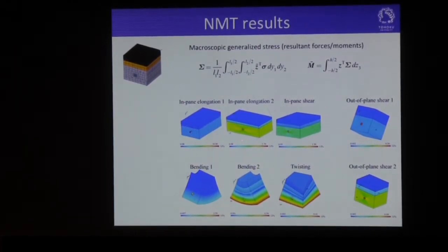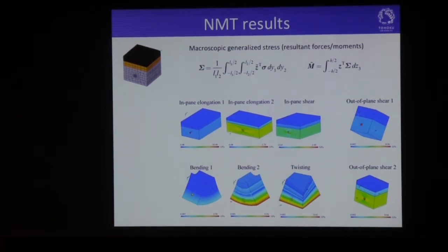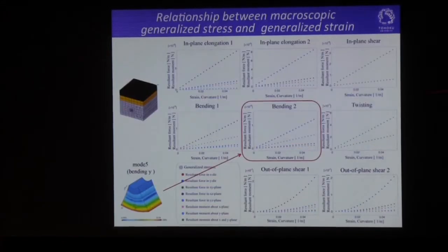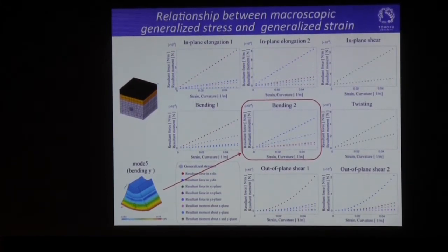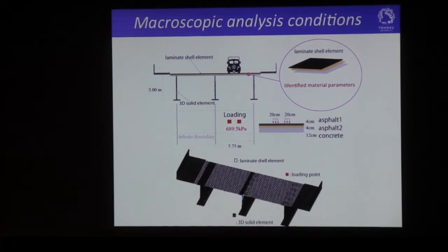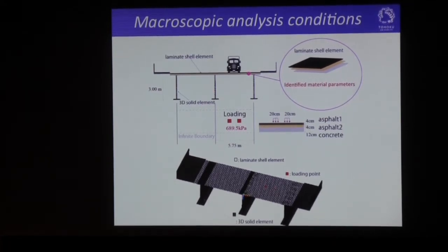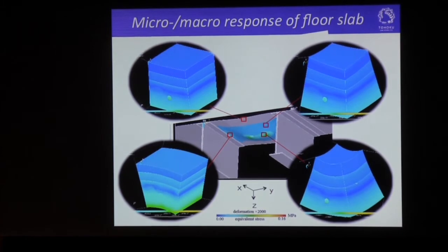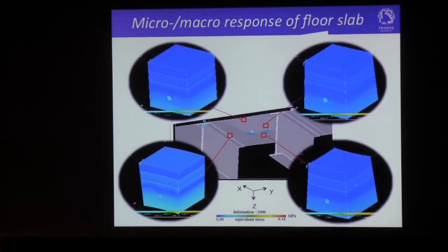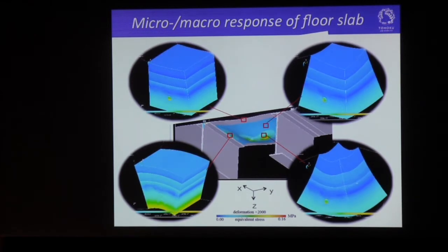As you can see, this is the in-plane deformation. This is the bending and twisting deformation. Here is also the out-of-plane deformation. Okay. Then we could have this kind of relationship between the macroscopic generalized stress and generalized strain. Then we identified some material parameters for each layer. Then we could make the macroscopic analysis that is set up in this figure. This is the bridge, the floor slab of a bridge. This is modeled by a laminated shell element here. Then we can have this kind of micro and macro response of the floor slab. This is the example of decoupled analysis of a composite plate here.